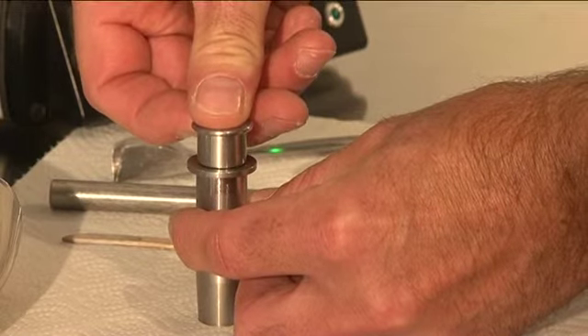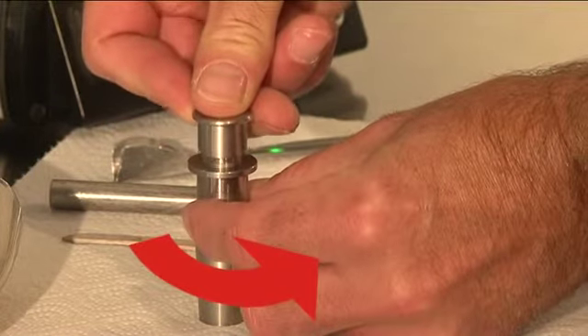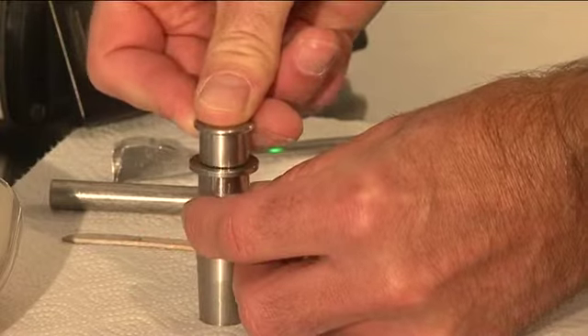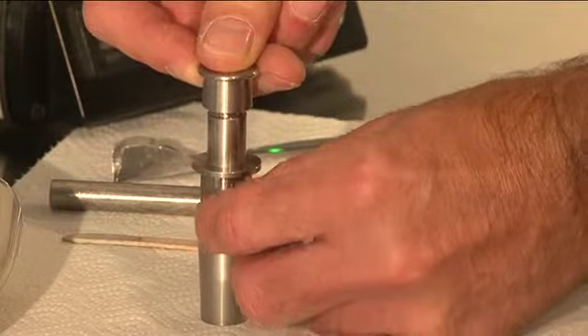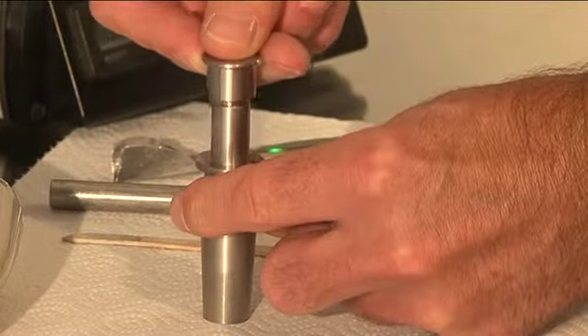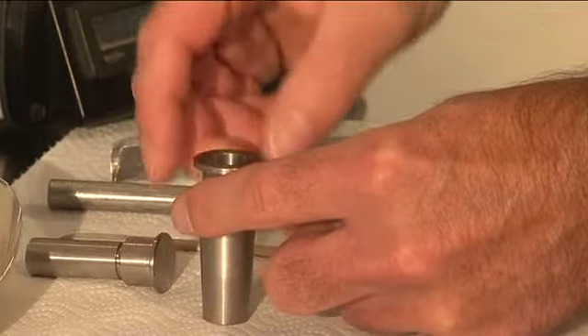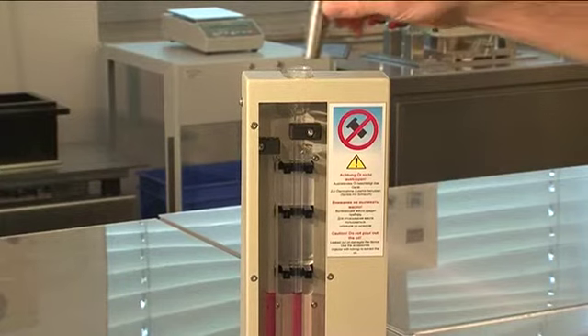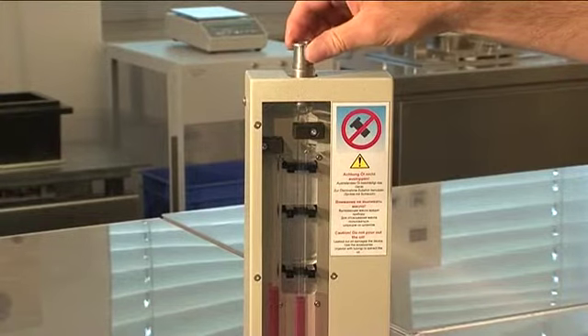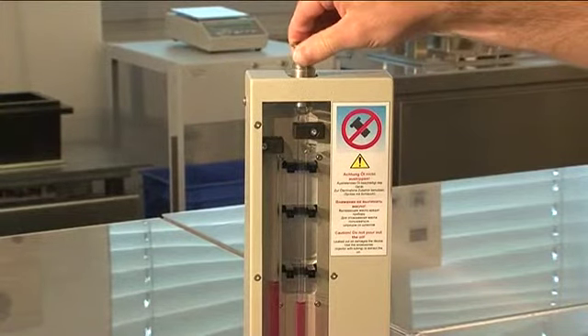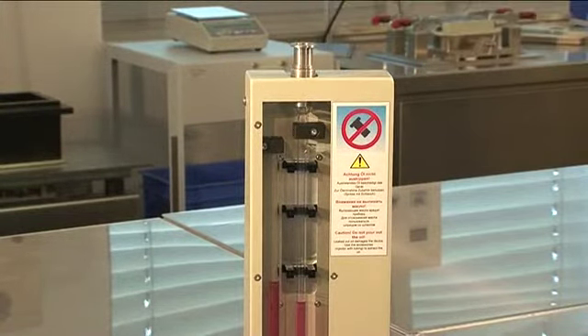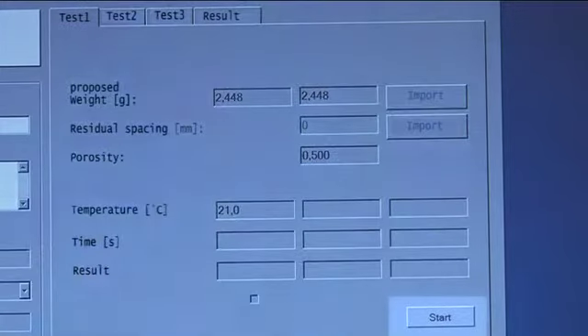Then slowly raise the plunger approximately 5 mm, rotate it through 90 degrees and press it onto the powder bed again. The bed is now compacted. Slowly withdraw the plunger without disturbing the sample bed. Place the cell with a lightly greased exterior into the glass cone of the U-tube. Briefly press the Start button on the PC. The test will now run automatically.